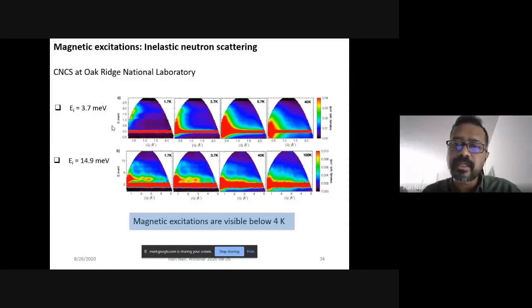As you increase the temperature, you would see that it becomes very, very broad. Now, whenever you see an excitation at very low Q, they are all magnetic excitations. Whenever you see something at high Q, they are from the lattice. They are phonons. The low Q are magnons.